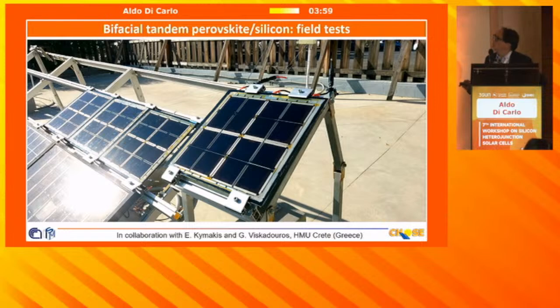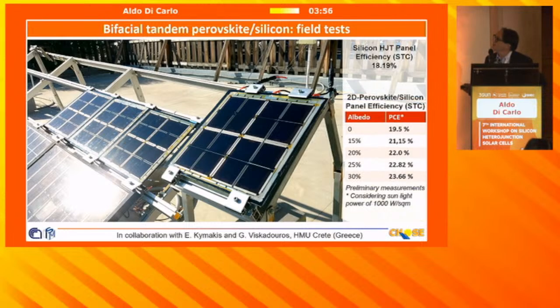So let me show you the results in this case. We started with a silicon heterojunction panel with an efficiency of 18.19%, and then we had the perovskite on the top. Without albedo it was 19.5, but of course the silicon solar cell was bifacial, the Enel or 3Sun cell, and then with albedo you can increase the efficiency. Of course, this is a fictitious efficiency because it's referred to one sun, so 1,000 watts per square meter.